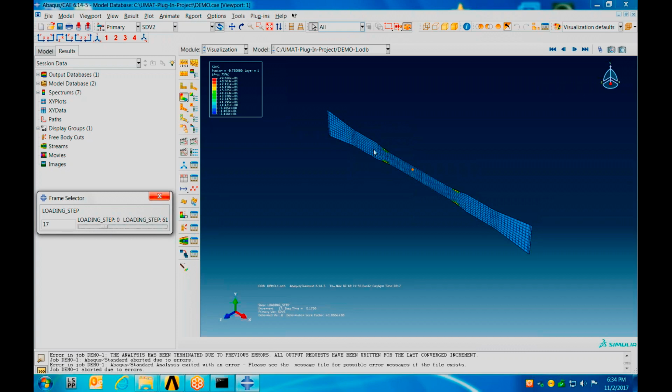As we walk through each incremental step, we can observe damage taking place and accumulating in the area where the specimen tapers from its full width at the tab to the narrowed width at the beginning of the gauge section. This zone appears to be experiencing increasing damage, resulting in the likely failure of the specimen in this region.